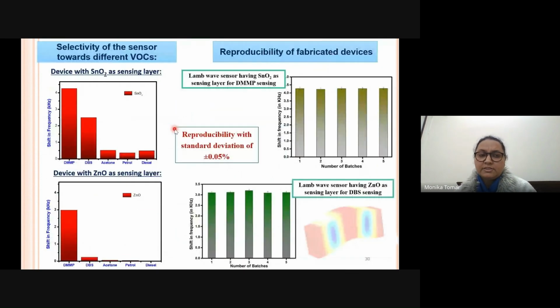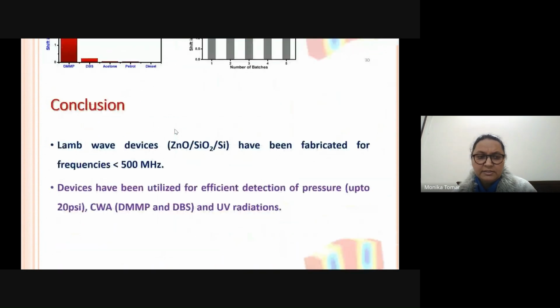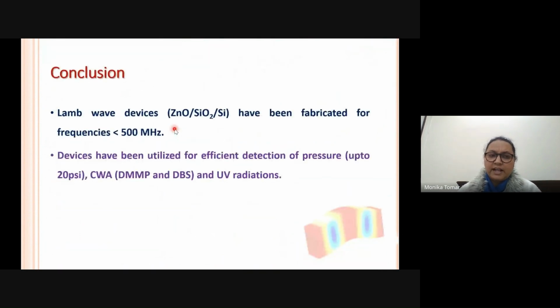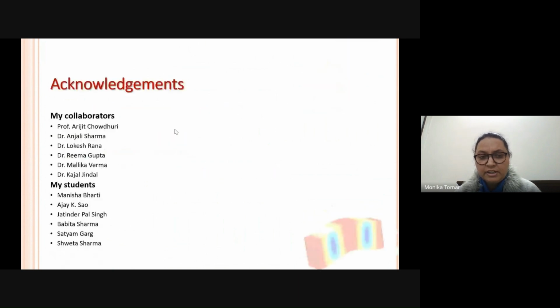We also studied the selectivity and reproducibility of these devices, and we found the devices were working very well. When fabricated in different batches, they showed similar results. So in conclusion, the Lamb wave devices, fabricated using the zinc oxide, silicon dioxide, silicon structure, have been fabricated for frequencies less than 500 megahertz, and these devices can be utilized for efficient detection of pressure, chemical warfare agents, and UV radiation.